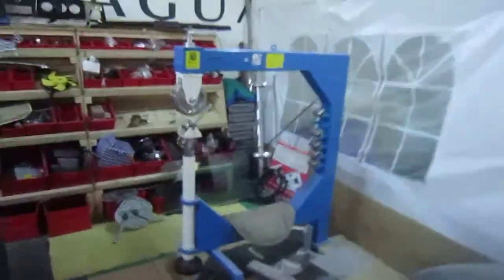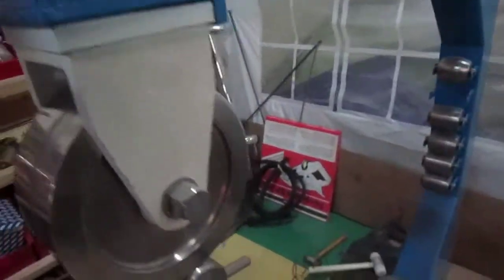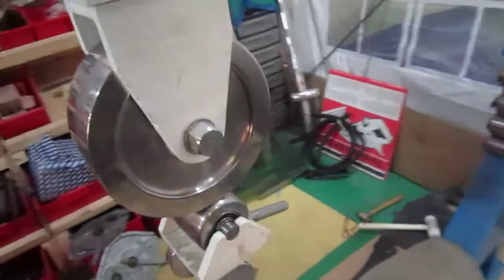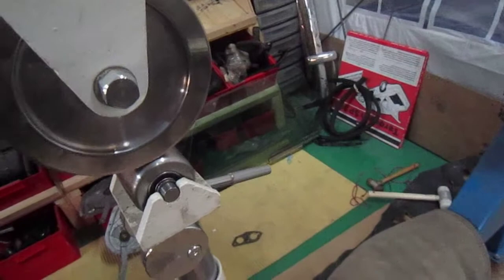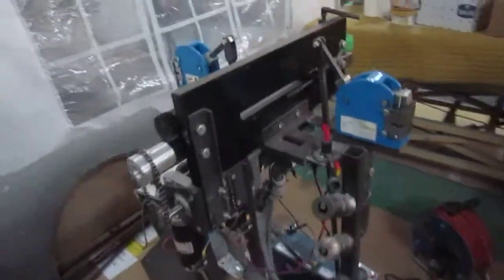So what we did was take it over to this machine here — this is the English wheel. What I did wrong really was I put too much tension in this wheel. You can see this is how it tightens. I just put a little bit too much tension in that wheel, and that's what caused the problem. So it's my own fault. I have a lot of experience with wheeling, and I only really use it to pre-wheel steel plates where we're going to put a bead in it with this beading machine.